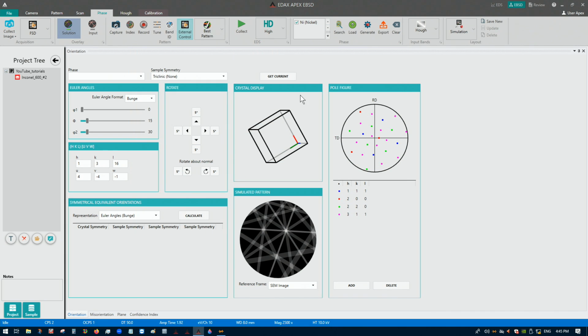And the database is fairly extensive. If your material is not in the database, you can load a phase file and generate the phase structure for this, okay? I have done this with random materials that are not in the database, so that can be done as well. But obviously nickel's not that exotic, so this is already perfect. You do want to give the system the least number of phases possible, okay? So if we know that the material is only nickel in terms of its phase, that's all we want to give it, okay? So we're just going to leave it alone at nickel.